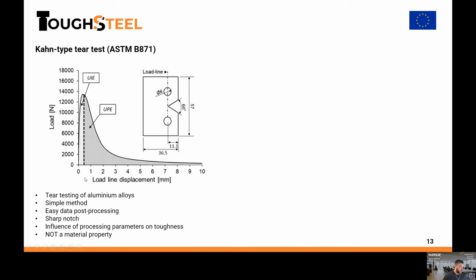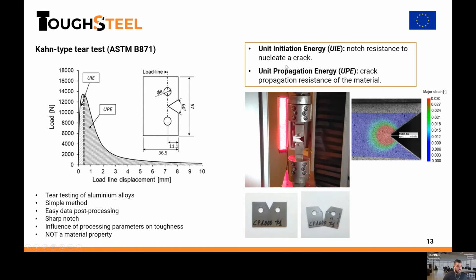Then by integration of the area, you can also obtain these two parameters: the unit initiation energy, which represents the area up to the peak load and is related to the notch resistance to nucleate a crack, and then the unit propagation energy, which is the energy of the area under the curve after the peak load until the final fracture. And this represents the crack propagation resistance of the material.